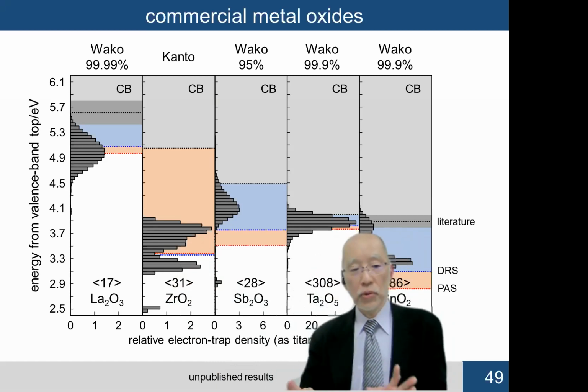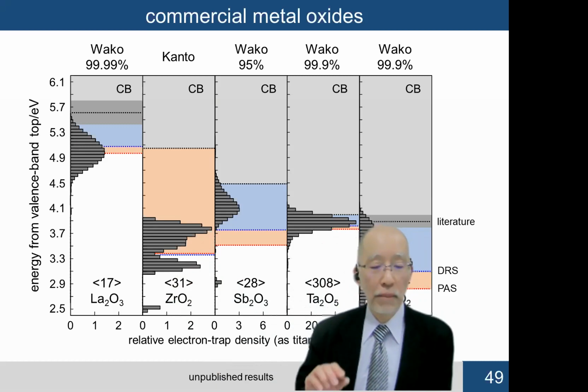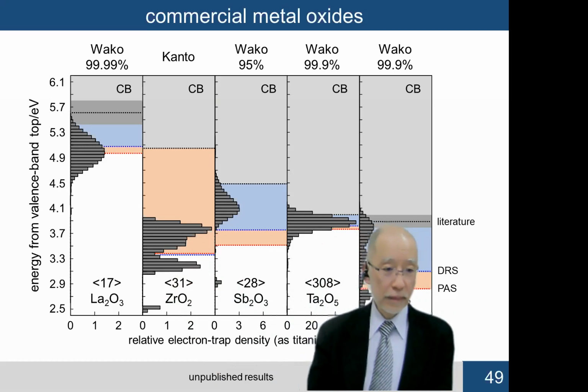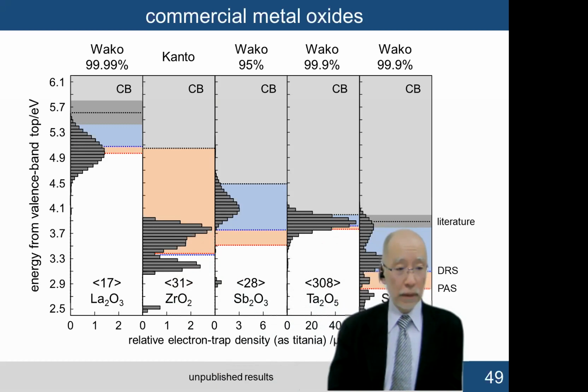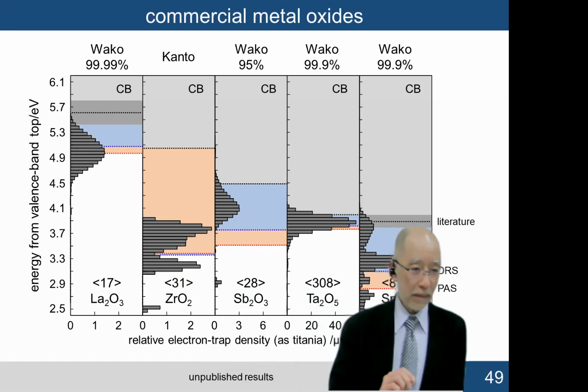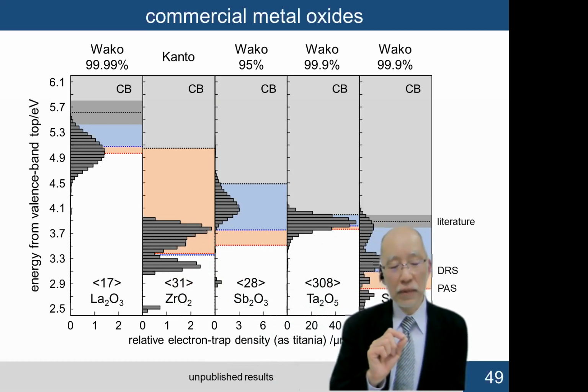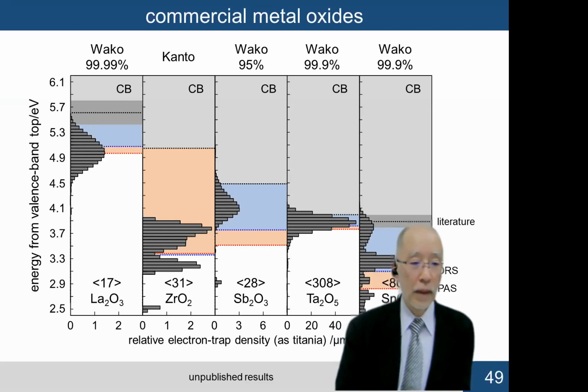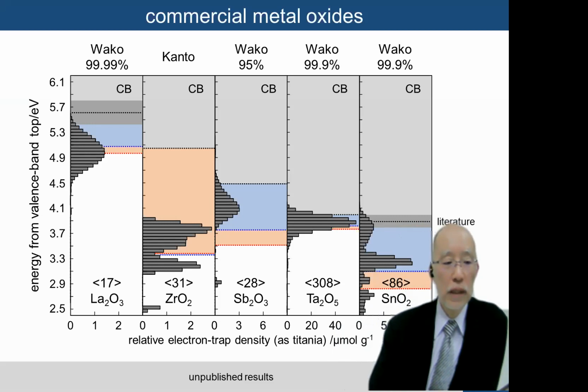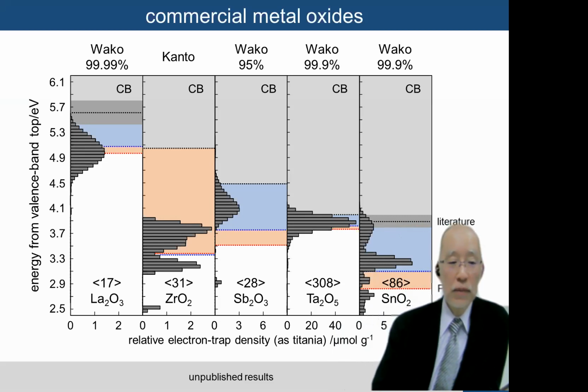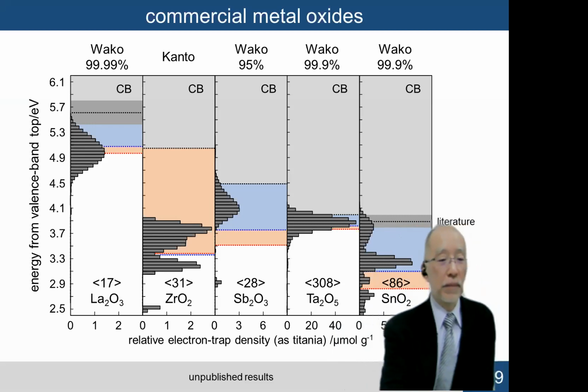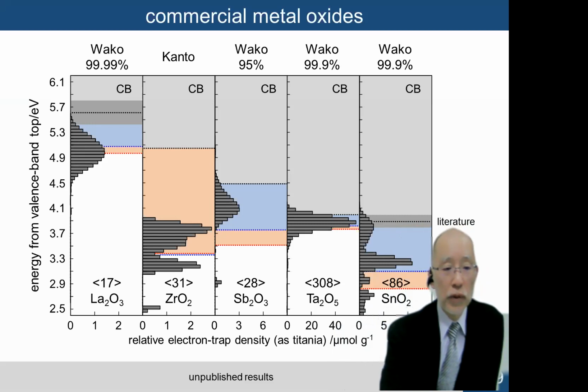And probably this is not proportional to the specific surface area, but depends on the amount of doping or impurities. And that is a very important point. Any material can be detected to some extent. If we can detect a very small signal by using a special technique, it is possible to analyze those samples. But anyway, we have no limit of measurement. And if you have some materials to be measured, we are very happy to accept them. Even if that is an insulator or p-type semiconductor, it might be possible to measure. So anyway, we can measure those patterns even for insulators.